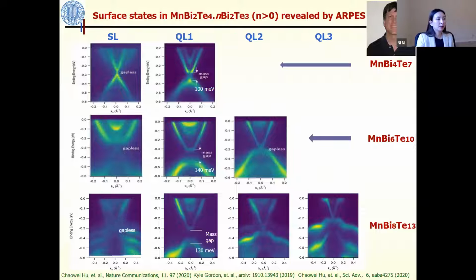And indeed, this is what Dan saw. For 147, he has done very careful ARPES measurement using a beam size of around 10 to 20 micrometers. By that way, he was able to identify 2 distinct surface states for the 147, 3 distinct surface states for 1610, and 4 different surface states for 1813.